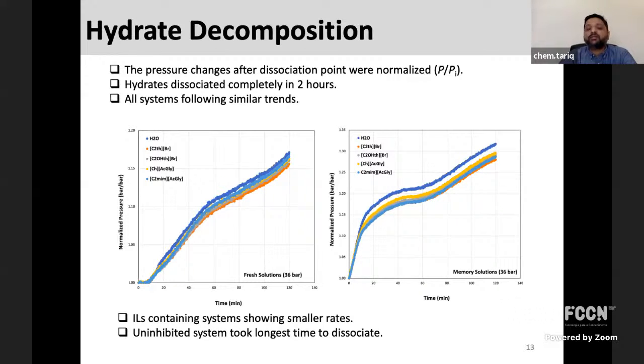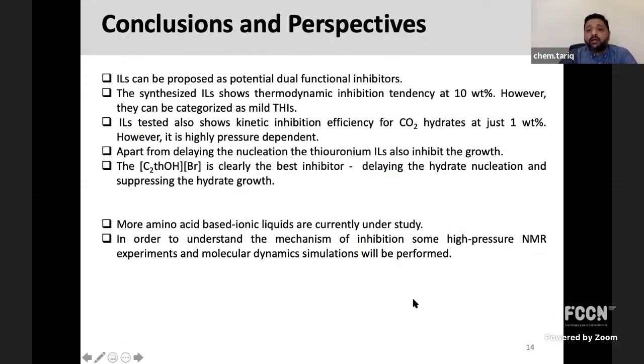So at the end, I would like to conclude that ionic liquids can be proposed as potential dual function inhibitors, because at 10 weight percent they can act as thermodynamic inhibitors, but they are mild inhibitors. And ionic liquids can also show kinetic inhibition efficiency at just 1 weight percent, but it is very highly pressure dependent. Similarly, apart from delaying the nucleation, the thiouronium ionic liquids are inhibiting the growth rate of hydrates. And thiouronium hydroxyl bromide is clearly the best inhibitor, delaying the hydrate nucleation and suppressing the hydrate growth.